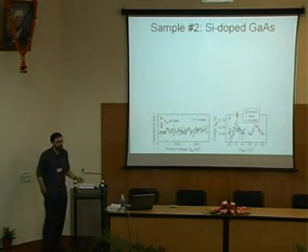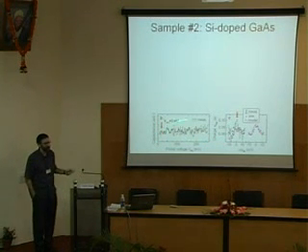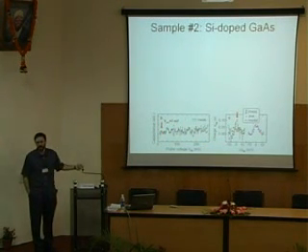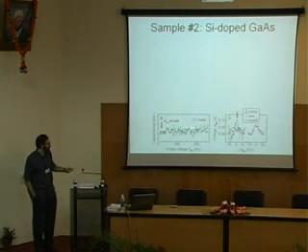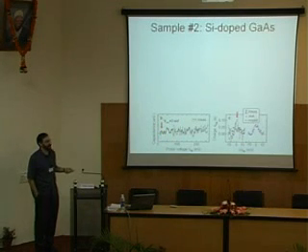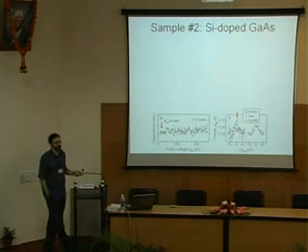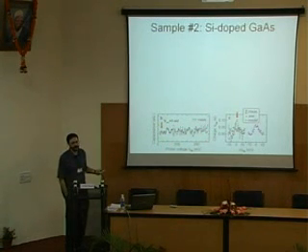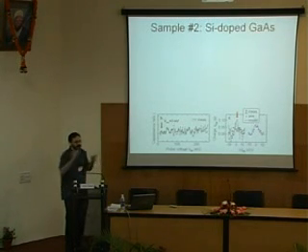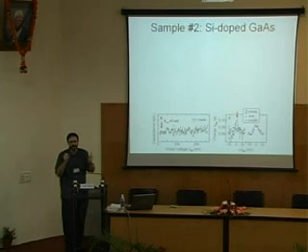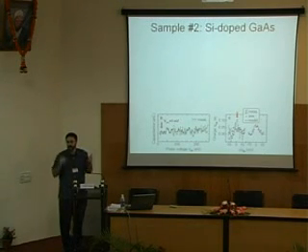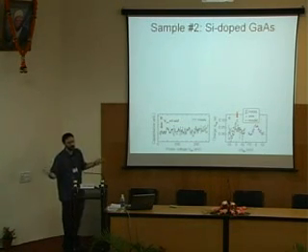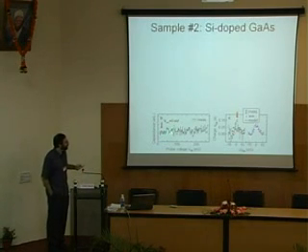We don't see one peak or just a few peaks. We see a whole mess of peaks. And of course, when you look at these data, many people say, "You're showing me a bunch of noise." It does look like a bunch of noise. Basically, if you have a random distribution of dopants and they're close to each other, you see a random distribution of peaks. You have lots of interactions, lots of different spacings between different dopants. It's not surprising that their quantum levels are getting shifted in random ways due to all this charge sitting around. But it's not a bunch of noise, actually.